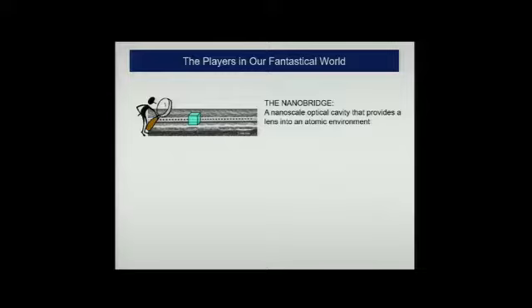And so the players in our fantastical journey are the nanobridge, which is this, which I'll be talking more about. It's a nanoscale optical cavity that provides a unique and very high precision lens into an atomic environment. And a little bit of the dimensions, we'll come to it again. This is 1 micron. So this nanobridge is about 200 nanometers in width. It's several microns long. And you see these holes that are punched into the nanobridge are on the order of less than 100 nanometers apart from each other. So that's one player, the nanobridge.